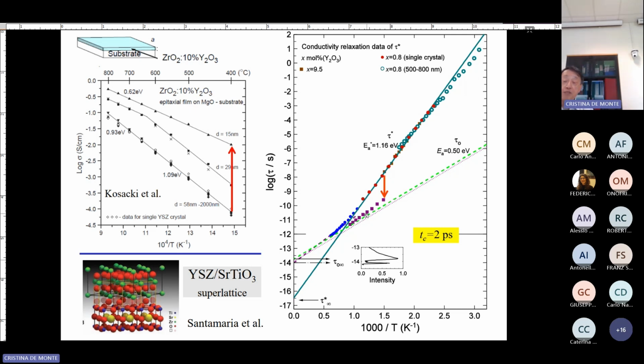Okay, and this is tau zero calculated from each of these points here. One last thing, and then I'll quit: you can calculate tau zero from this tau alpha, the conductivity. This is due to oxygen conductivity, oxygen hopping. And then you go to this, you get this value here. The activation energy is much smaller because of the relation of the two as defined by the coupling model. And you extract both of these to infinite temperature.